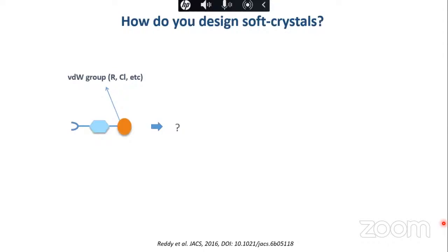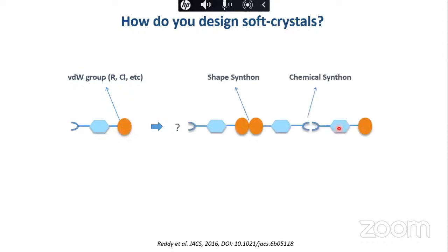So for example, if I use this group, and in addition to this, I use another group, for example a van der Waals group, instead of keeping the same group, I just keep something else. These groups will not go with this, right? They don't interact with each other. This is because this is highly polar, and this is almost like a dispersive group. So in that case, these groups close back simply. They just try to fill the space, and since they are of the same type, they will interact with each other, and these are mostly van der Waals interactions. And then aromatic groups pi stack, and these groups interact again with themselves, and then you get a dimer synthon. So this is how you will be able to build the structure.